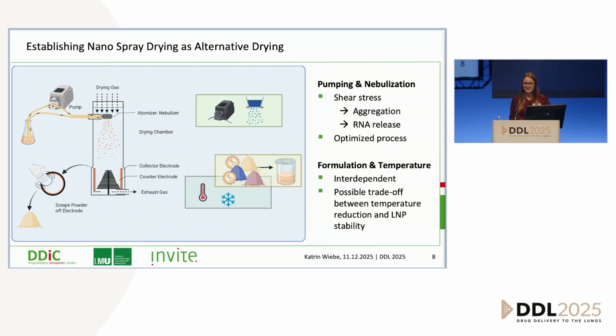The other thing I want you to see is that you really have to think formulation and temperature as interdependent. It is possible that there is a trade-off between the lowest possible temperature and the best LNP stabilization efficiencies. And we hope that in the future, we will find a formulation where we can really optimize this and find a maximum of stability at a minimum of temperature.